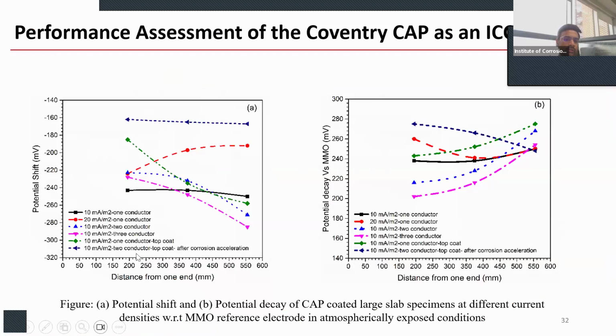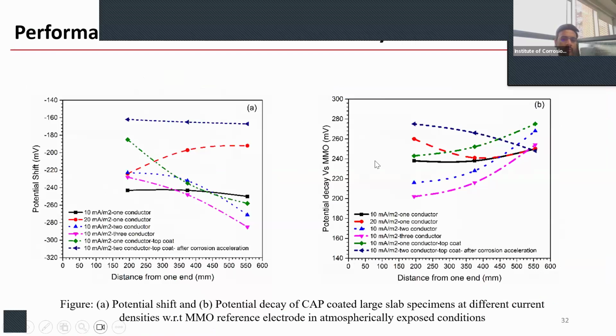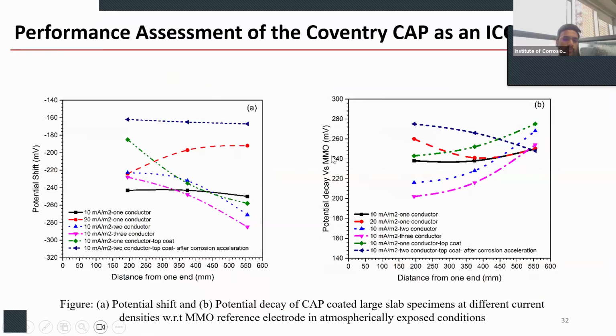So you can see that for all these current densities, we are able to achieve the 100 millivolt decay using the MMO inert probes, or the decay probes.